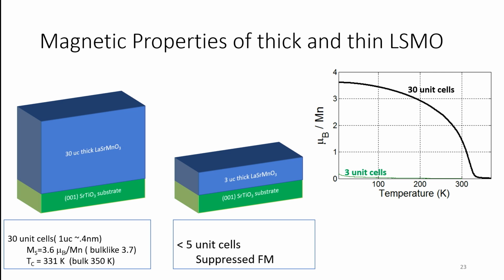But if you reduce the thickness by a factor of 10, so let's go from a 30 unit cell thick film to a 3 unit cell thick film, and again, this magnetization is normalized to the thickness, so if it was the same property, then we should see the same type of curve. We see that this 3 unit cell film has completely lost all its magnetic properties. And this is a really common phenomenon in a lot of thin film systems, where when you make the material very thin, you lose all the interesting properties which you had in the bulk forms of these systems.